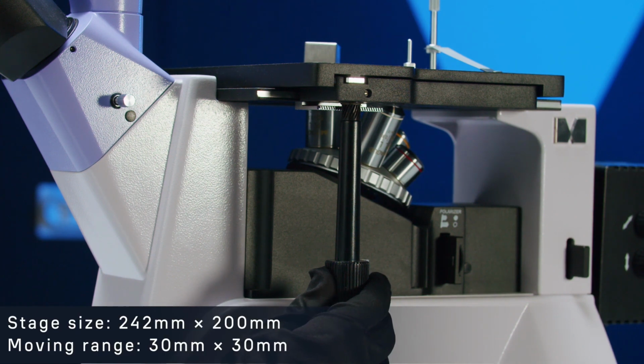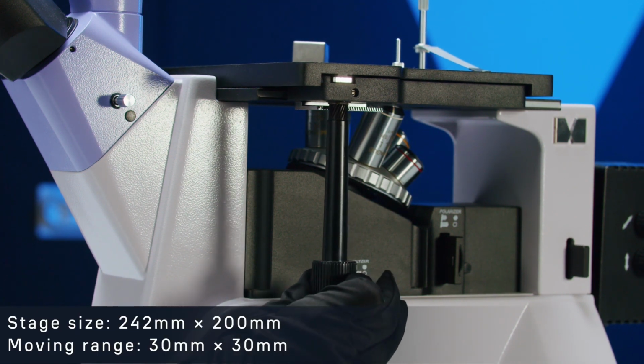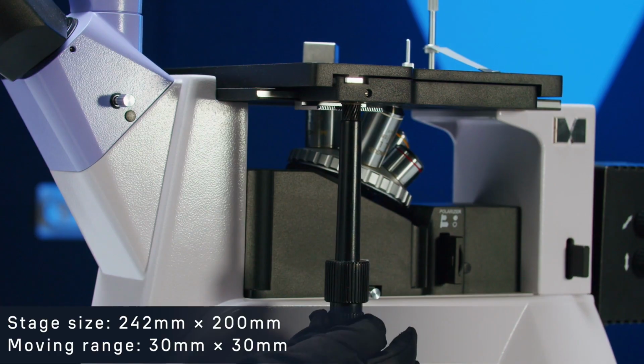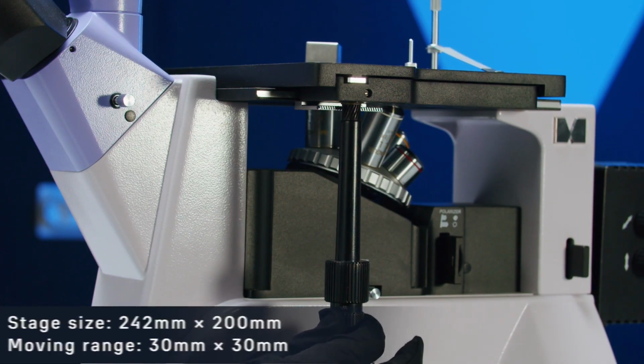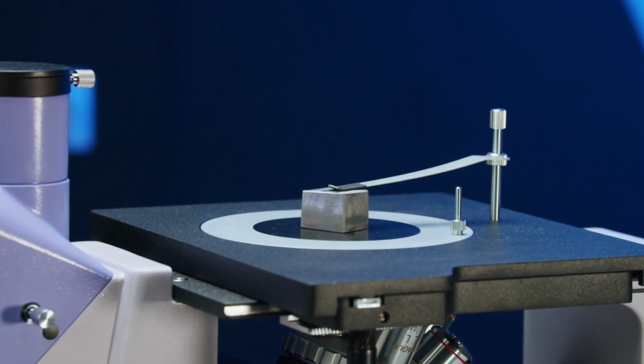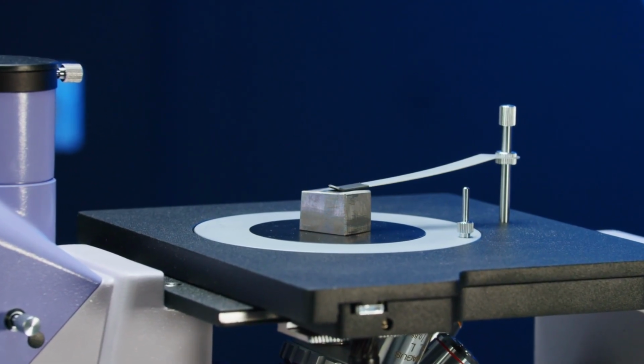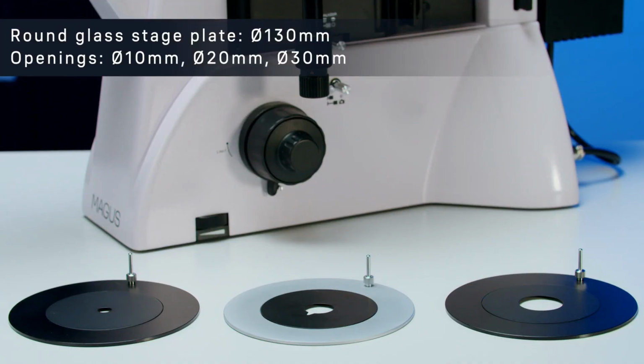Stage. The microscope stage is equipped with a 2-coordinate movement system. The movement range is 30 millimeters along both axes. The specimen is placed on a circular insert in the center of the stage. The set includes 3 interchangeable inserts with holes of 10, 20, and 30 millimeters in diameter for samples of different sizes.